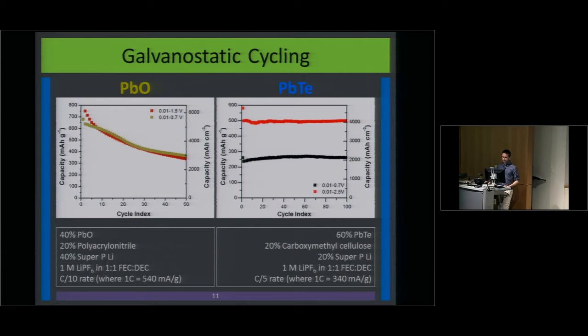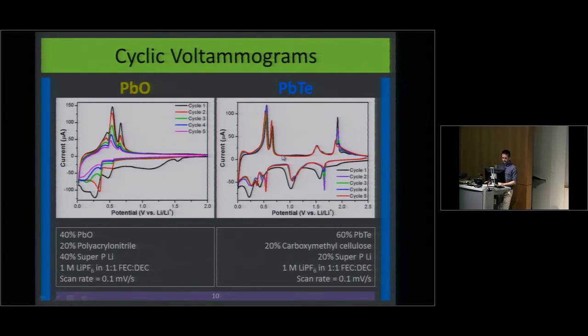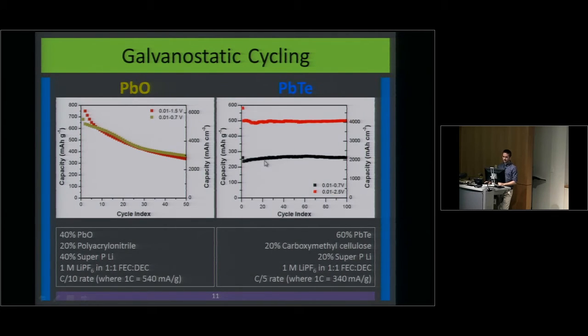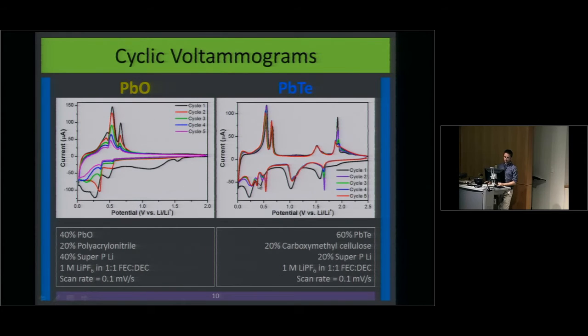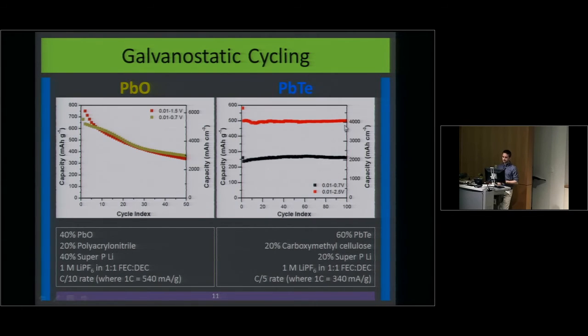So you can see there are 2 lines up here. For the lower line, the black line, I'm only looking at lithium insertion into the lead, which is this left part. But if I include the tellurium reactions over here, that's what this upper line is.